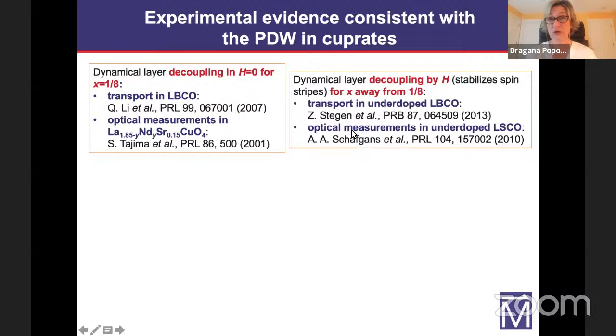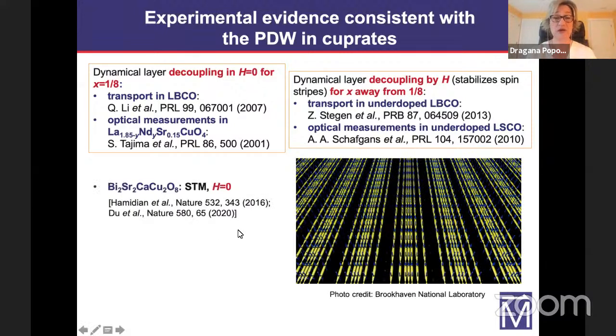So here, there were also experiments done on materials that were away from 1/8 doping, but it was found that in the presence of a perpendicular magnetic field, which stabilizes spin stripes, they were also able to find evidence for the suppression of the interlayer Josephson coupling. So all of these experiments were done on the lanthanum 214 family, and more recently there has been STM work in Seamus Davis's group on BSCCO, in which they found evidence consistent with the presence of paired density waves. So this was done in zero magnetic field.